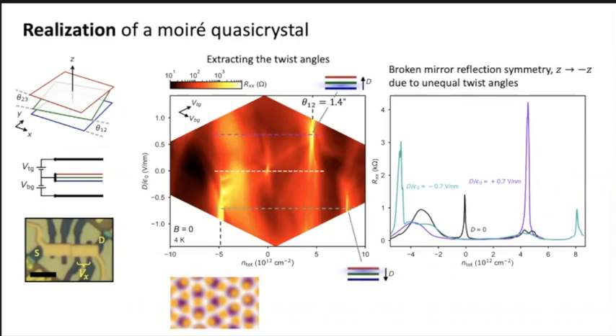We can, in the same way, polarize the system with displacement field and with density such that now it is the top two layers which we're looking at. When do we go through the band insulator state for the top two layers? Because the bottom layer is mostly unoccupied. And that tells us that that angle is actually 1.9 degrees. And because we know we assembled them with alternating twist, okay? Not identical, but alternating, we know that this is actually minus 1.9 degrees, yeah? So now we have the two Moiré patterns, okay?